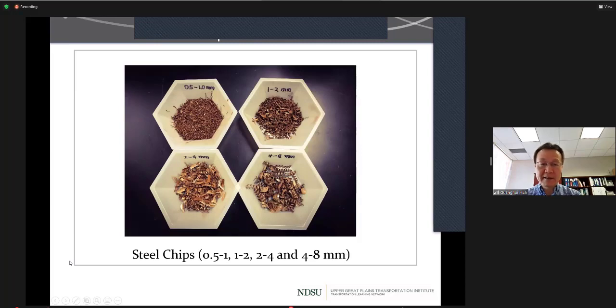So once again, these are the materials that were used for the column study, and we sieved the material into different sizes. 0.5 is considered fine material, then 1 to 2, 2 to 4, and 4 to 8 millimeter. And the 4 to 8 millimeter size is considered coarse material.